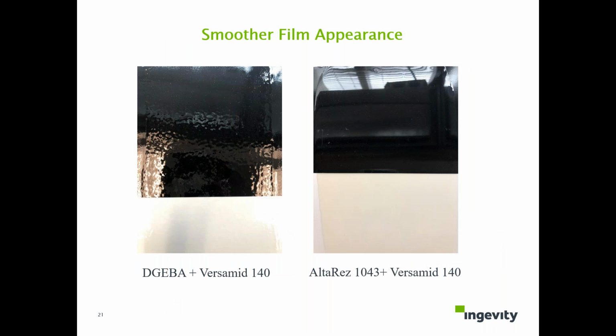So some films show the same trend with amidamines, and diol epoxy with amidamine. This amidamine comes from Versamid 140. Our diol epoxy cures so it's very transparent and a very glossy and smooth film, and the control sample shows not a smooth film. So I think this is a big improvement.